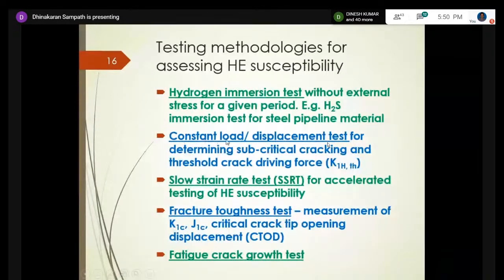The second one is the constant load or displacement test. This is used for measuring subcritical cracking and also the threshold crack driving force, which is the K1H threshold. This is the minimum crack tip stress field required to begin the crack propagating. Also, for accelerated testing, this one will take a lot of time, and they expose it for a certain period depending on the severity they need.